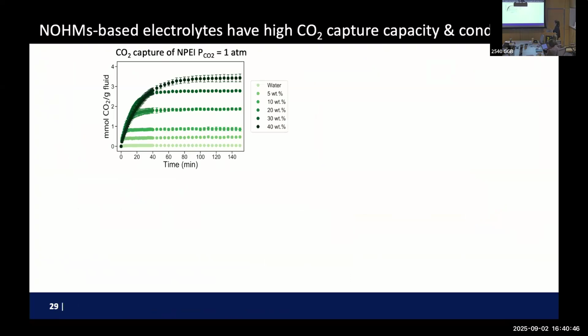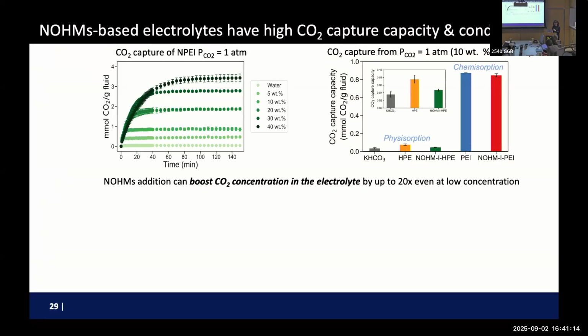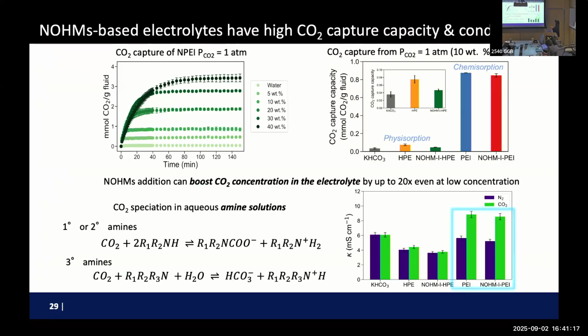So if you look at the data, this is just water-based electrolyte. CO2 capture is very tiny. In fact, if you look at a lot of data for CO2 reduction, electrochemical reduction data, they start with this concentration. Even then, conversion was very low at the time. Now your catalysts are getting better, you will be running out of CO2 to convert. So now if you add more NOHMs, you have a huge increase in CO2 concentration in your electrolyte. This is great. And in fact, if you're using chemisorption, in this case, you can put a lot more CO2, and also conductivity goes up because you start making carbamate and sometimes even bicarbonate. So we got excited. So let's convert this absorbed CO2 in this electrolyte into something useful.